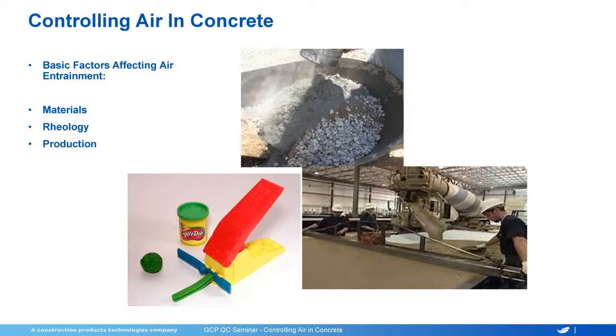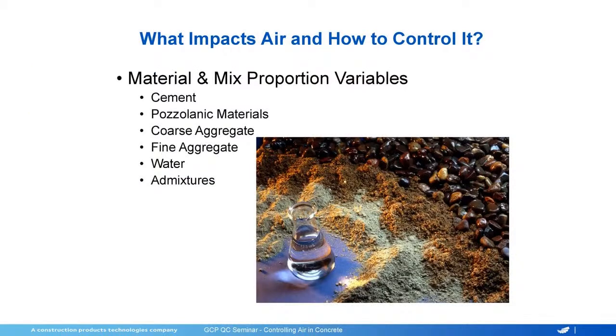The same with SCC. We can have a 25-inch slump flow that gets to 25 inches in just a matter of seconds, or we can have a 25-inch slump flow that you can take a break, go get a cup of coffee, come back, and it's still creeping out to 25 inches. So the materials, the rheology of the mix, and your production process, those are the keys, and doing those consistently, those are the keys to getting the concrete to turn out. And I know what you're thinking, right? Easy to say, hard to do. Totally agree with that. So looking at the materials, and we'll jump ahead.